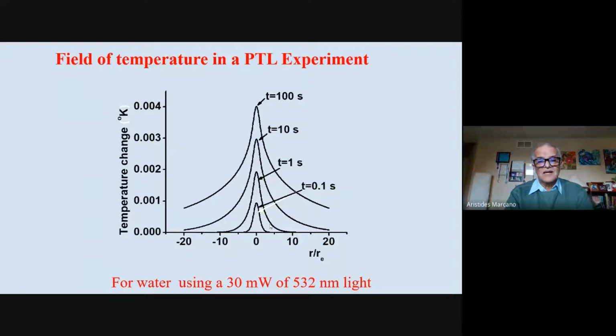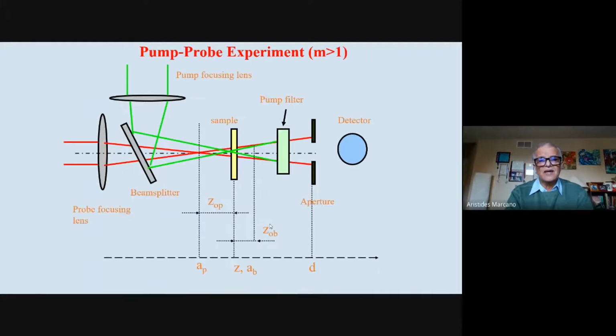Good. So you can calculate easily this temperature, and then, of course, you can calculate the phase. You can go, okay, we know the phase. If you know optics, you can calculate what happens with the beam at the far field using these diffraction approximations. Usually we use the typical classical Fresnel approximation, considering that we are looking at a distance which is much bigger than the size of the thermal lens, and that approximation is very valid there.